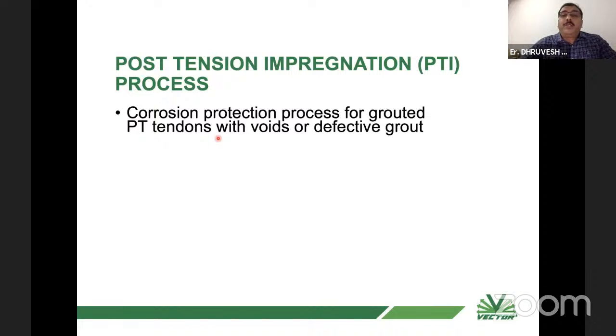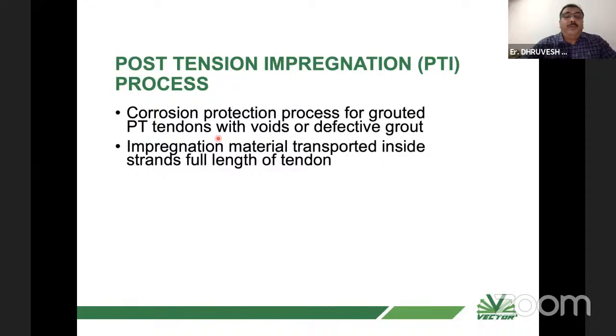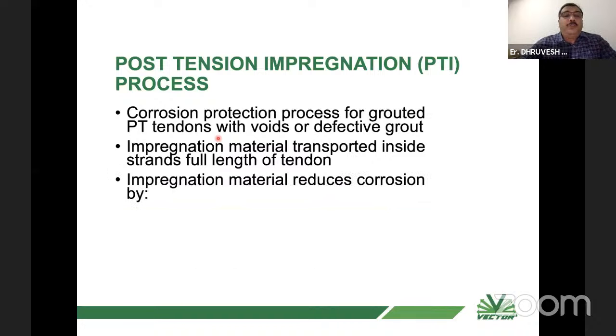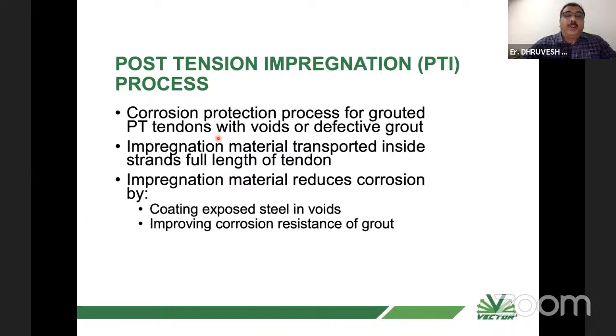The corrosion protection process for grouted PT tendons with voids or defective grout can be done with an impregnation material, which is transported from inside the strand for the full length of the tendons. It may be 20 meters or 100 meters. I have done a treatment for 80 meter long strands without any joints. The impregnating material reduces corrosion by coating exposed steel in the voids and also improving the corrosion resistance of the grout around the strands.